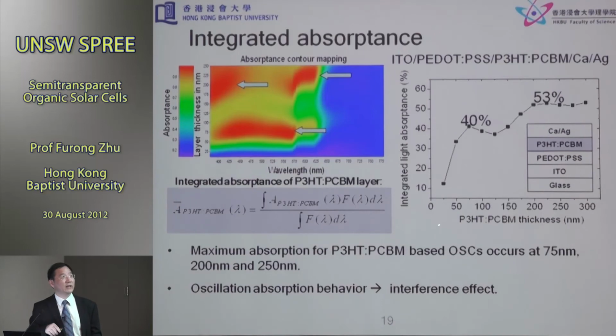But we know that for organic semiconductor material, because the mobility is relatively low, a cell which absorbs the same amount of light or even more with a thinner layer is more preferable. So it depends on the application. If this is a tandem cell, probably you need to look at a layer corresponding to that kind of relative absorption. Because this is only for P3HT:PCBM blend. If you're using, for example, PCDTBT:C70, probably the peak will be located in various places. But essentially the physics is the same, right?